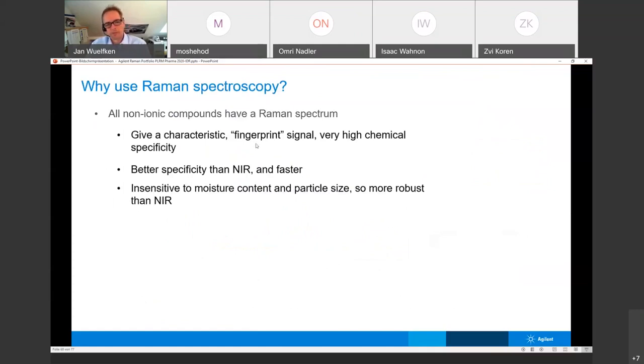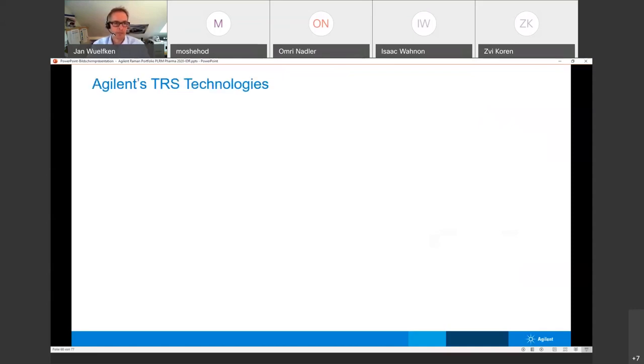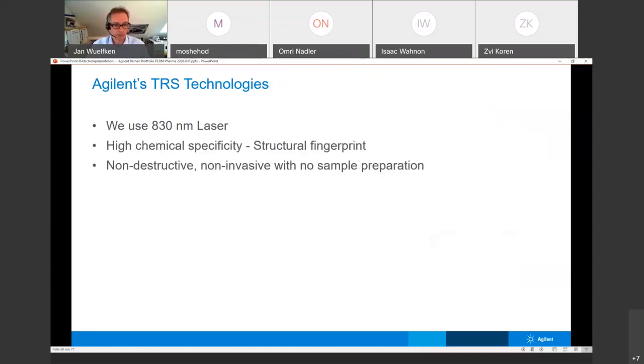We use Raman, it gives you a fingerprint, we know this, it's more specific than NIR. So there's also NIR spectroscopy to do this tablet analysis, but Raman is faster and gives you higher specificity, so we don't have the broad overtones. And it's insensitive to moisture content and particle size, so it's much more robust to get methods out, in comparison to NIR. Relatively inexpensive and adopted by the regulatory authorities. So all the TRS-100 are adopted by the regulatory authorities. So we have non-destructive fingerprint measurement. You can even analyze your tablets after the TRS measurements without any problem.